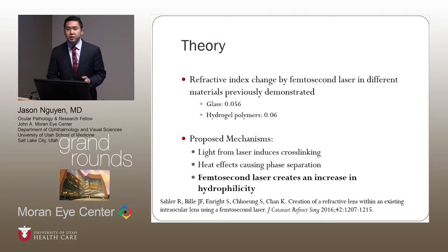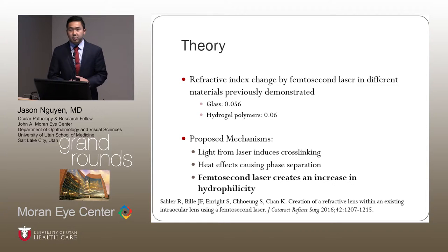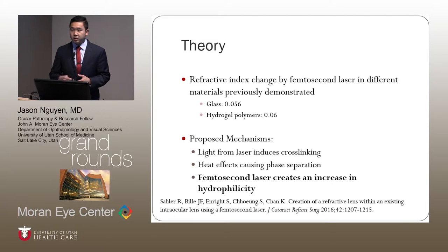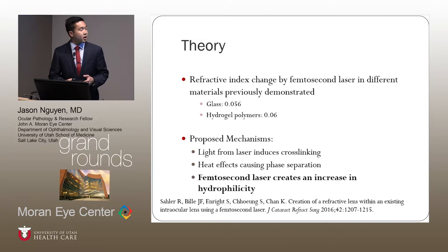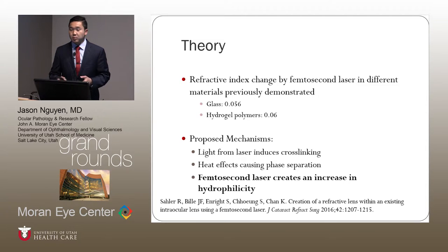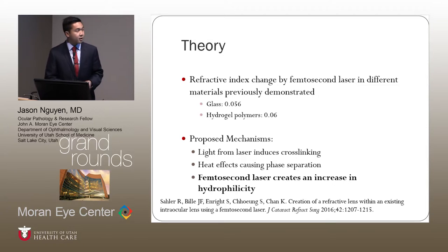But the one I wanted to focus on today is the one that the Perfect Lens Company has used — using the femtosecond laser to treat an area which will cause that area to increase in hydrophilicity. Once that treated area has been treated, we see that it absorbs water, and the absorption of water causes a decrease in refractive index.